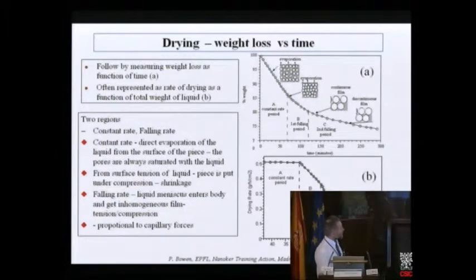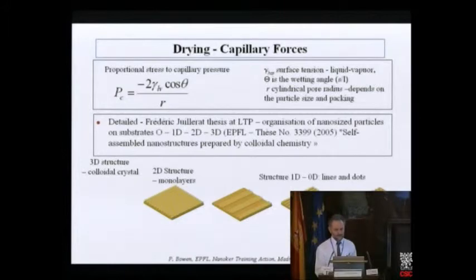So now we're looking at the rate, so this constant rate period when we have just the evaporation from the liquid surface, first falling rate period when we get the continuous film still through our porous structure, and when we get the second falling rate period when we get the discontinuous film and we have to sort of transport the liquid through the vapor phase. And basically, as we pass this critical point, we get capillary forces, which then can drastically crack our material. The capillary forces will depend on the size of your pore, the surface tension of the liquid and vapor, and the contact angle.